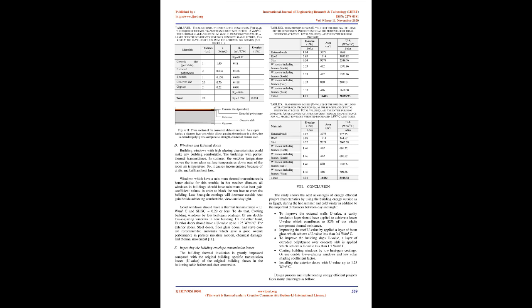To improve the roof U value, a layer of foam glass is applied. The U value was 1.70 W/m² °C before the change. Thermal transmittance reached 0.18 W/m² °C after, less than 0.4 W/m² °C. Figure 10, the converted roof construction cross-section. By adding a thermal insulation layer, foam glass, the roof construction is improved. Furthermore, the two bitumen layers act as a vapor barrier. The roof thermal transmittance is improved until it reaches 0.18 W/m² °C. C.